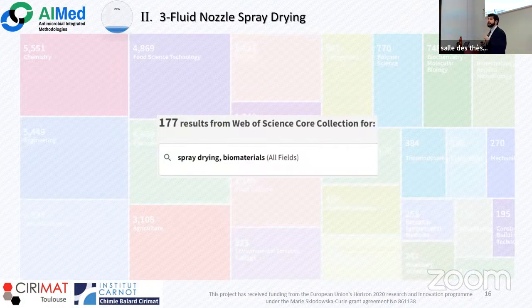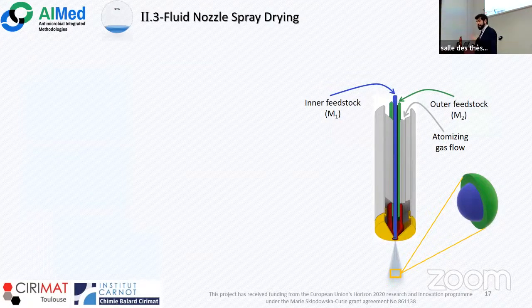There are just a small fraction of papers that involve spray drying and biomaterials. Furthermore, we want to control the structure, as we said before. So for that reason, we wanted to use the 3-fluid nozzle spray drying. It has a setup that is similar to the one that I just showed, but with a nozzle that is concentric and that can allow us to use 2 different feedstocks and to obtain a biphasic drop that then can hopefully be dried in a correct structure.